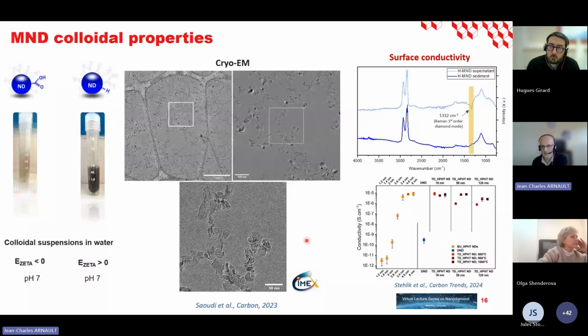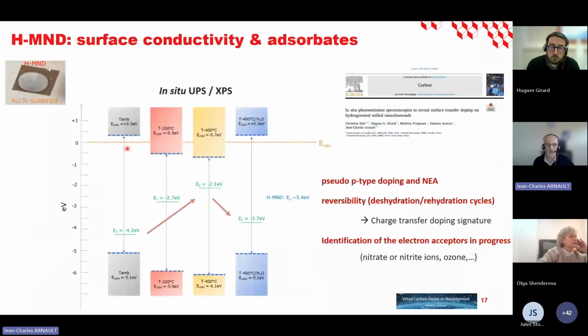So to investigate that, we performed in situ UPS and XPS spectra on these particles. We started with these particles sprayed on a gold silicon substrate. And this is the condition of the initial substrate. So we rebuilt the band structure. And you can see that for the initial hydrogenated milled nanodiamond, we have this negative electron affinity expected for bulk diamond, and a location of the Fermi level very close to the valence band. This suggests a p-type doping of the sample.